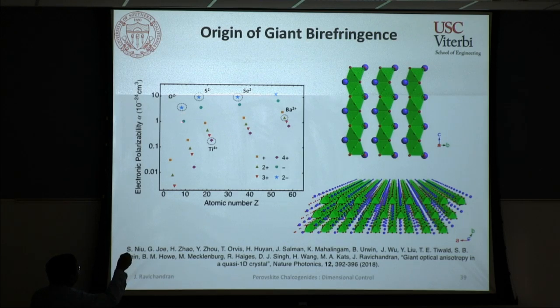So it turns out taking the polarizability of individual elements and trying to distribute them along two different directions is not an easy challenge. And we were lucky enough to come across this type of structure that we got interested in, where it forms a 1D chain compound, and also we picked the right type of elements. For example, sulfur has very high polarizability compared to oxygen, and that's what allowed us to get very large index difference along the two different directions.